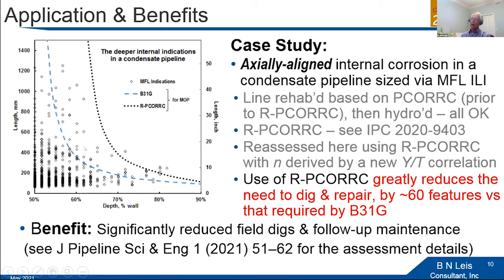By avoiding the modeling error, we've avoided, in this case, digging roughly 60 features and repairing roughly 60 features. But if you take the corrosion rate that was active here and advance this population in length and depth, what you see very quickly is that you'll add a tremendous number of features such that 60 becomes 600. The benefit in this context of using an accurate, precise criterion is that you've significantly reduced the number of digs and the follow-up maintenance that's required.